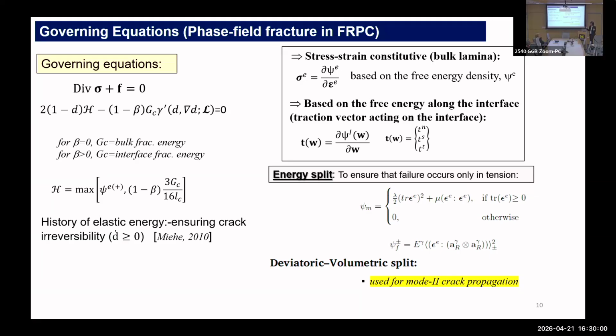But remember, there is no displacement jump. The displacement jump is now a smoothened approximation based on the Taylor series approximation that I just showed you. So it doesn't require any nodal tracking of how the interface is separating, which is what you do in classical cohesive zone-based modeling. You can avoid those completely. And then in addition to that, of course, the method requires that fracture happens only in tension. So you can do all sorts of decomposition to ensure that fracture does not happen in compressive loading. If you have a shear-driven situation, then you can decompose your elastic energy into deviatoric and volumetric parts and then make the deviatoric part drive your fracture, etc.